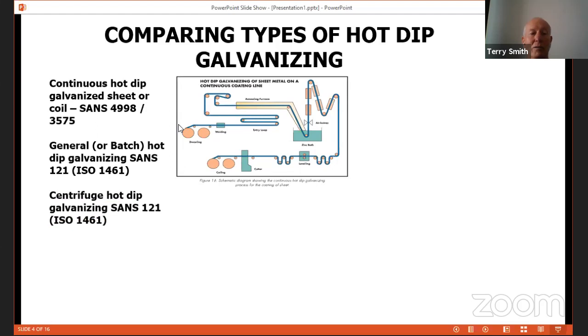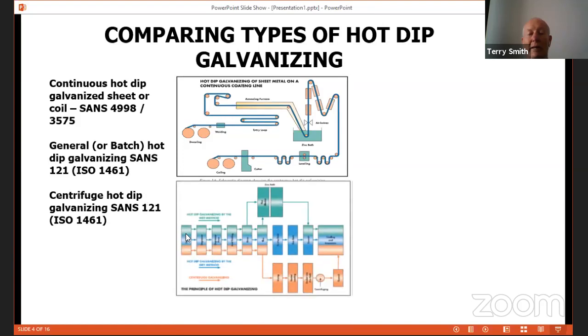General or centrifuge galvanizing are both done to SANS 121. So this is the process. It starts off with jigging, degreasing, water rinsing, acid pickling, rinsing again, final fluxing, drying, and then into the zinc bath where the reaction takes place. Centrifuge galvanizing goes through the bottom process here.